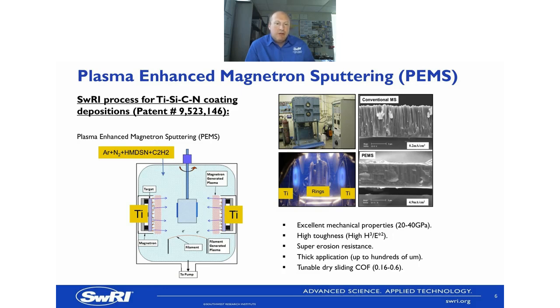Magnetron sputtering utilizes a magnetic field and an electric field to confine particles near the surface of the target. That increases the ion density and results in a high rate of sputtering. Magnetron sputtering is an exceptionally versatile method for thin film deposition. Other deposition methods are limited to the materials they can use as the sputtering target. So the source material can be almost anything with magnetron sputtering, since it doesn't need to melt or evaporate the material. The sputtering deposited film will have a composition that closely matches the source, and it will adhere to the substrate better than evaporated films.